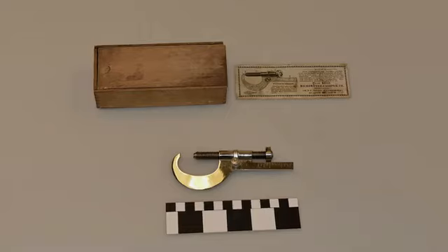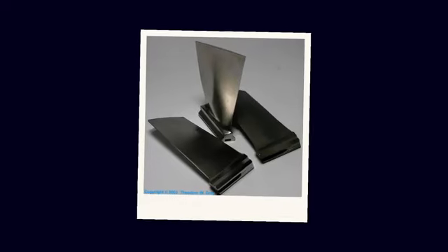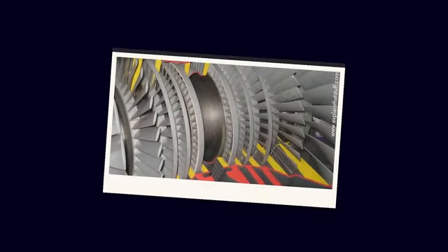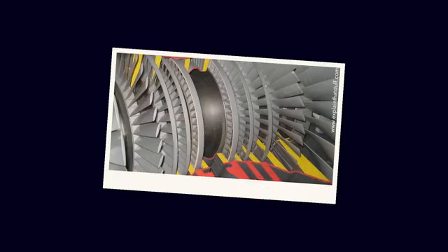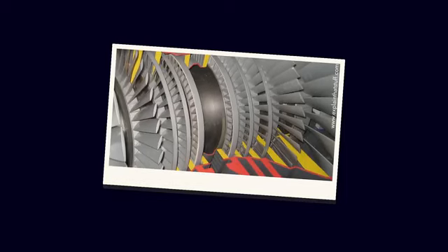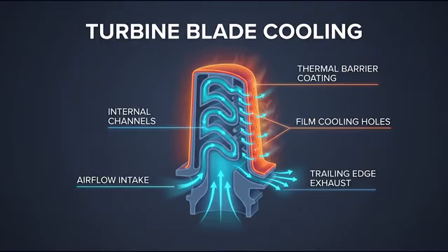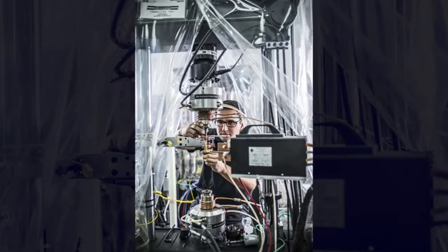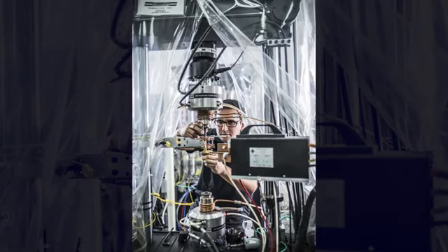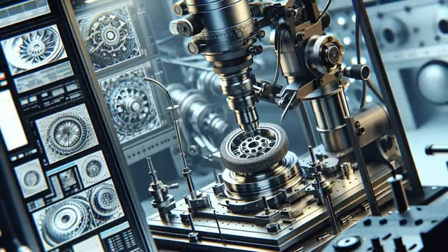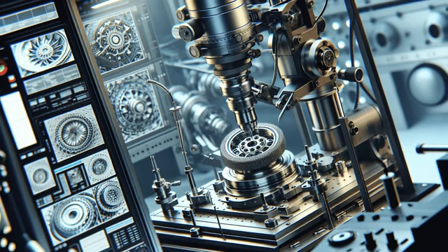The choice of material matters enormously. Jet engine turbine blades must endure temperatures hotter than the melting point of the very alloy they are made from. Engineers achieve this through hollow internal cooling channels, barely a millimeter wide, cast directly into the blade. Some advanced blades contain over 20 separate internal passages. The cooling air that flows through them drops the effective metal temperature by as much as 300 degrees Celsius.